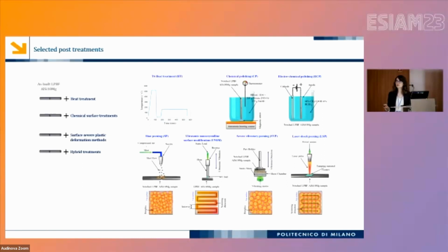And then we have considered severe vibratory peening, which is again very similar to shot peening, but in this case we have a limited number of shots enclosed inside a chamber and accelerated in order to impact the surface of the part. And lastly, we have considered laser shock peening. We are considering the individual effect of each of these treatments, and also the combined effect together with chemical or electrochemical polishing, in order to see how much they affect the mechanical response of our samples.